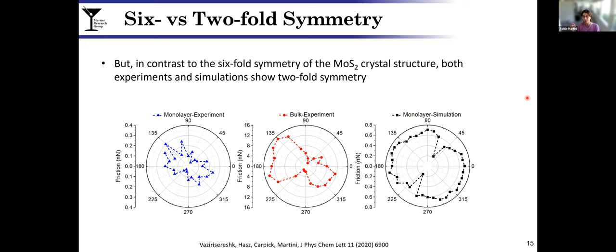We performed experiments and simulations scanning along these two directions on the MoS2 surface, and indeed we see much higher friction as well as higher energy dissipation in the 30-degree direction, which corresponds to armchair. So again, this is pretty exciting because it's connecting friction to something that we know about the material.